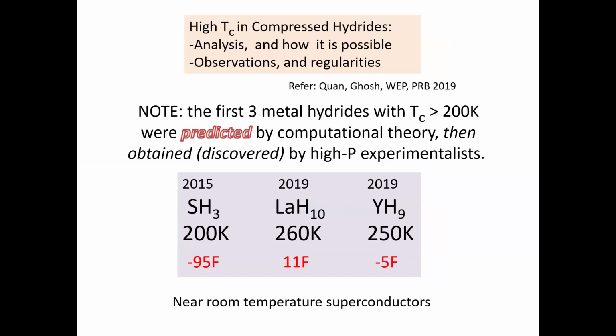In 2019, I mentioned lanthanum hydrogen 10 was discovered. 2 different groups. One got 250 Kelvin, one got 260 Kelvin. We always sort of quote the highest temperature. This is almost 90% of the way to room temperature from T equals 0. And then yttrium hydrogen 9 back at 250 again, right around freezing. No, a little bit below freezing here. A colder room in Kansas 2 weeks ago, something like that. Near room temperature. Okay, these are predicted computationally, and they were discovered then by high pressure experimental groups soon after.